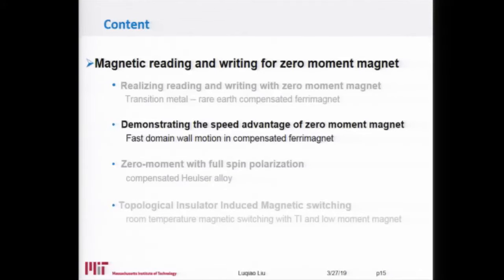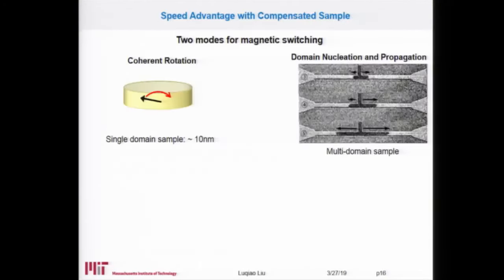So how are we going to show the speed advantage? Well, there are two possibilities, actually. The first one is to show the switching of a single bit magnet. So basically, you make the magnetic device into a single domain. That usually requires that you have to make the device below 10 nanometers. At the same time, you use picosecond or maybe hundreds of picosecond pulses to switch it. And then show that this switching speed is faster than previous magnetic devices.